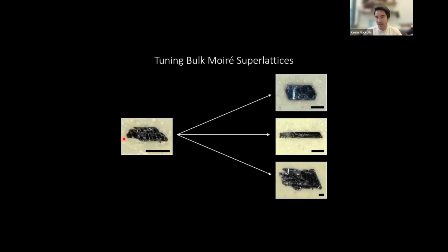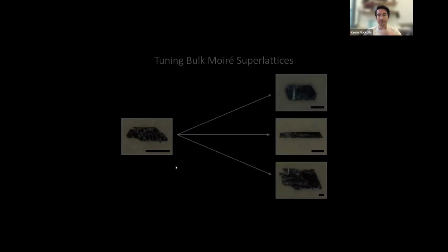So with this crystal in hand, I think it's good to think that we could try to tune the Moiré superlattice in this crystal using the tools of solid-state chemistry. And the idea here is that if this system is truly aperiodic, then the free energy of this crystal should be very flat. And so we should be able to stabilize a whole bunch of different incommensurate lattices because there's no one structure that is optimally favored in this phase space.